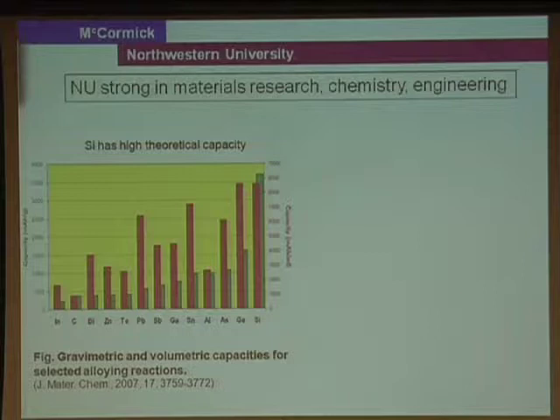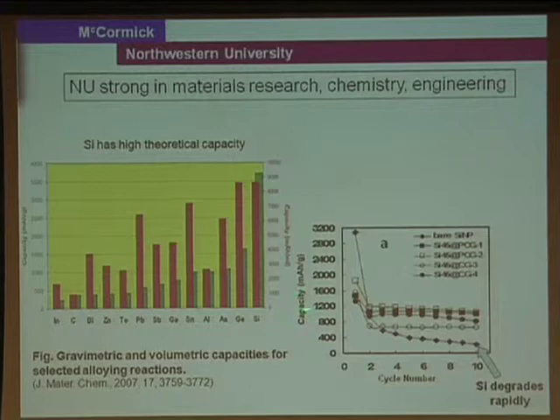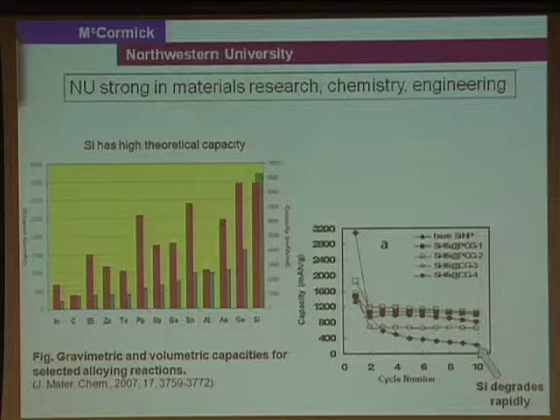Well, there are a lot of materials that are known to be able to store a lot more energy. Silicon, which was mentioned already, is one of them. About 10 times more energy density can be packed into it. So why don't people work with silicon? Well, one of the issues is that they die fast, and this is an example. If you look at the capacity, that's how much energy you can pack into that silicon, versus how many times you charge and discharge it, the cycles. That number dies off rather rapidly, it's right here.